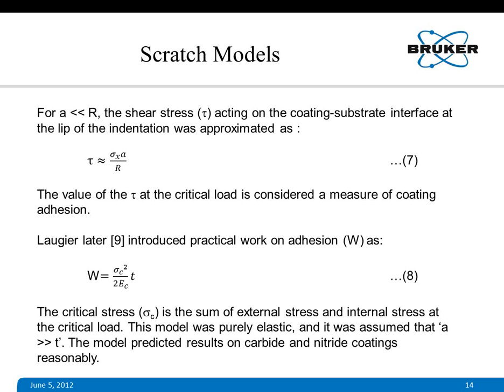Laugier later on also introduced work on adhesion for any particular scratch test, which relates to adhesion strength of any coating substrate system. And they expressed W equals sigma c square by 2 EC into T, where sigma c is the critical stress and EC is the Young's modulus of the coating. T is thickness. This model predicted results on carbide and nitride coatings reasonably.